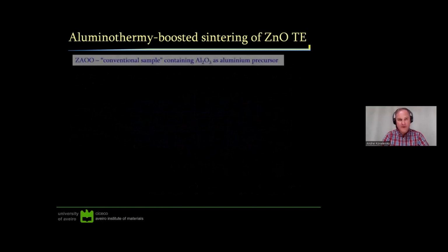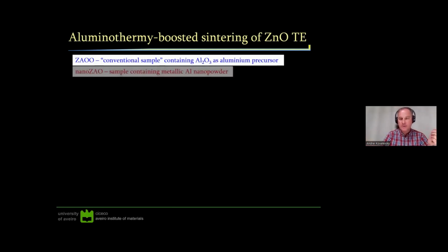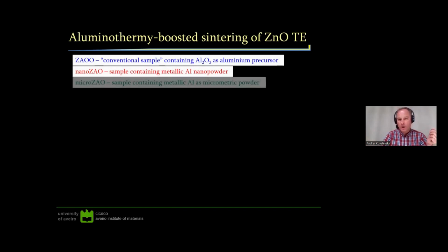So we prepared the reference material, zinc oxide doped with aluminum, prepared from conventional precursors like zinc oxide and aluminum oxide. Then there are two cases where we use metallic aluminum powder, as nanopowder or micrometric powder. And the results were actually amazing.